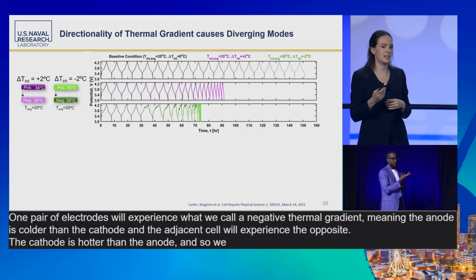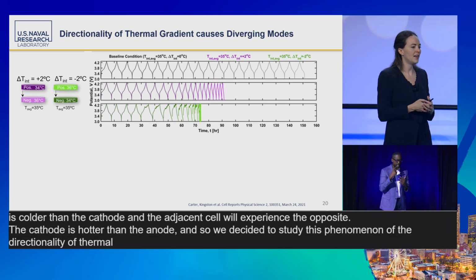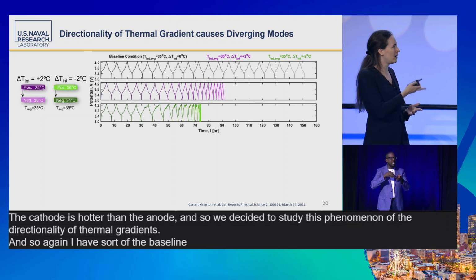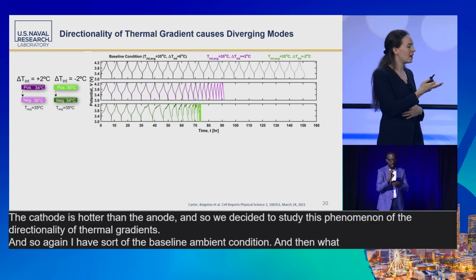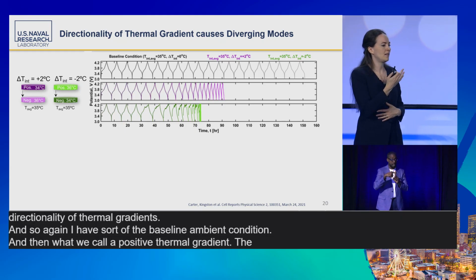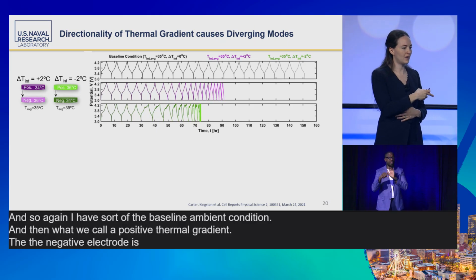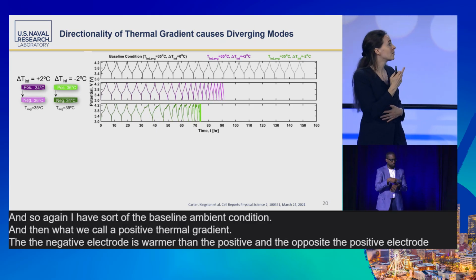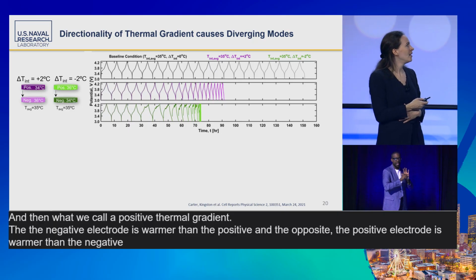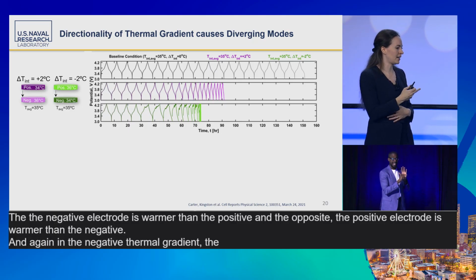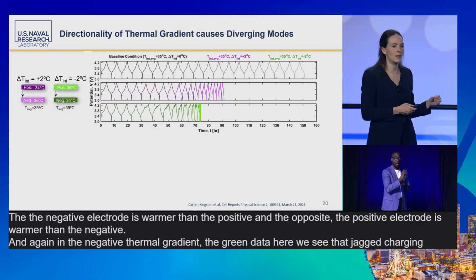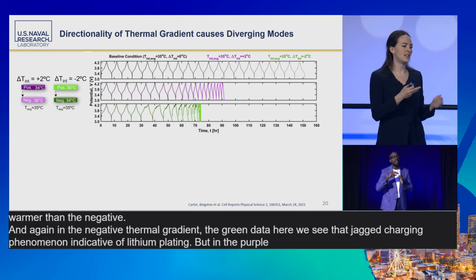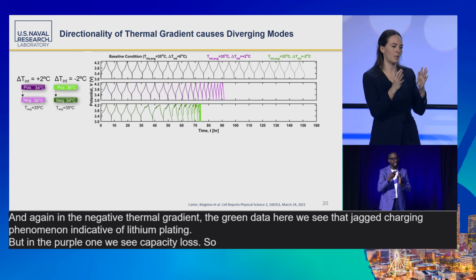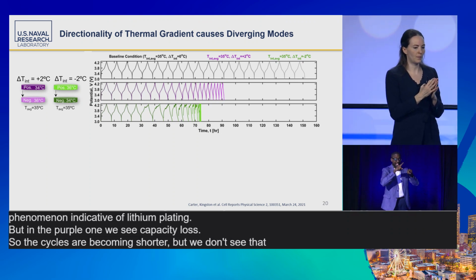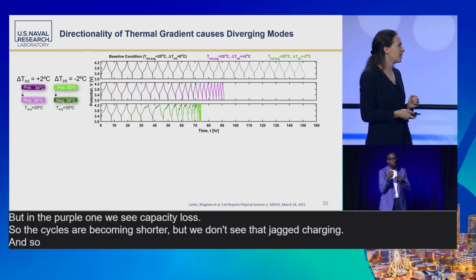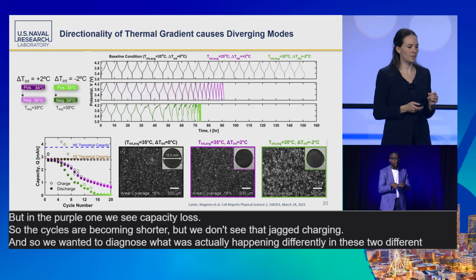And so we decided to study this phenomenon of the directionality of thermal gradients. Again, I have the baseline ambient condition, and then what we call a positive thermal gradient, where the positive electrode is warmer than the negative, and the opposite, the negative thermal gradient, where the negative electrode is warmer than the positive. In the negative thermal gradient, the green data here, we see that jagged charging phenomenon indicative of lithium plating. But in the purple one, we see capacity loss, so the cycles are becoming shorter, but we don't see that jagged charging. And so we wanted to diagnose what was actually happening differently in these two environments.